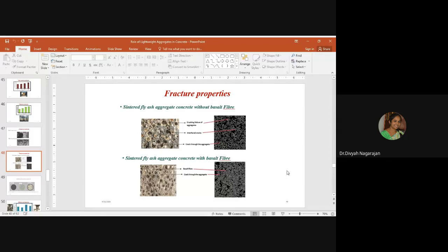But when basalt fiber is added, I don't say that the crack is fully arrested or that there are no cracks, but it enhanced the properties. See that the cracks through aggregates couldn't be avoided, but somehow to a considerable extent, the sintered fly ash aggregate concrete performed well when basalt fiber is added.